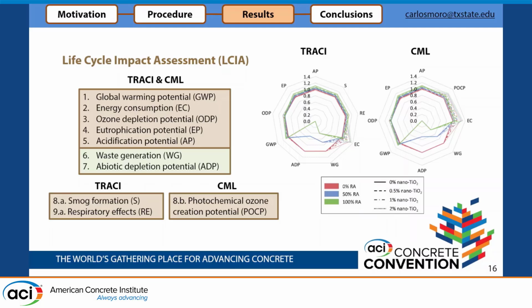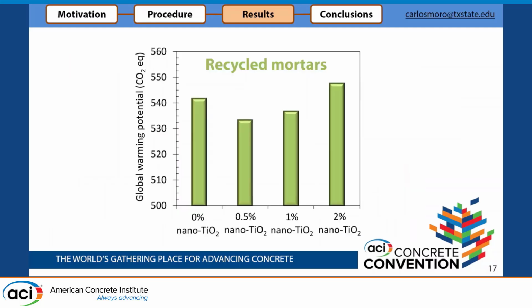But it also shows that, as expected, recycled concrete aggregate was very useful to help the waste generation and the abiotic depletion, and that the nanoparticles have a comparable performance compared to the reference sample with no nanoparticles, except for the energy consumption that is higher whenever you are producing these nanoparticles.